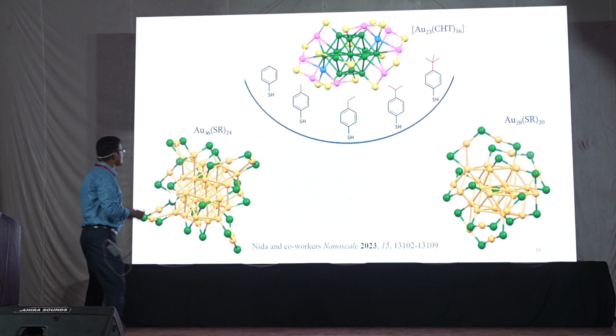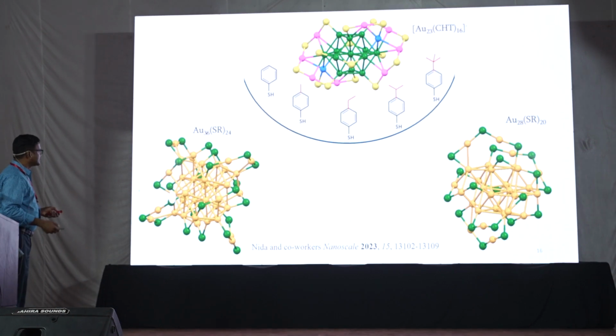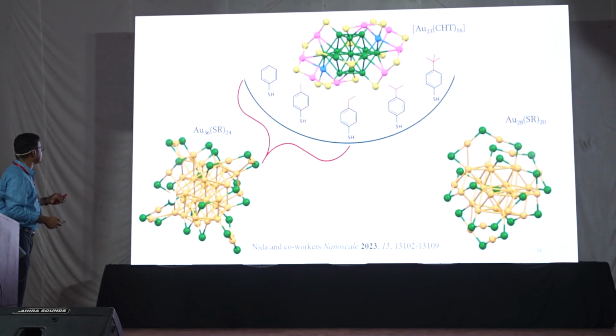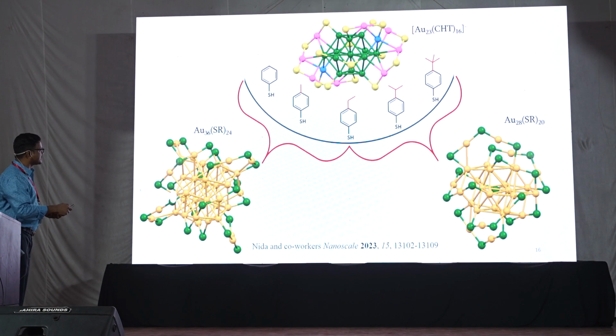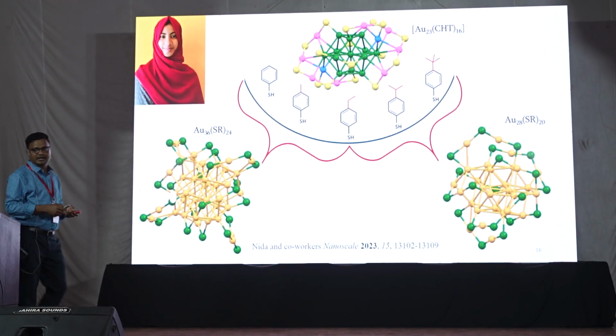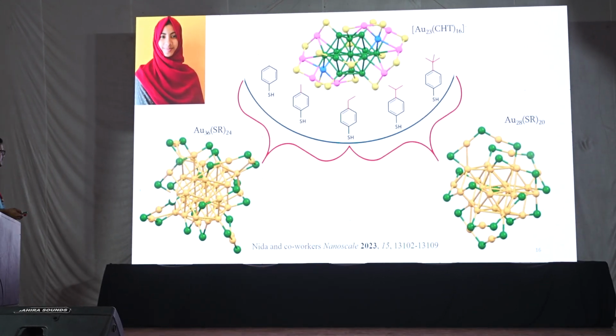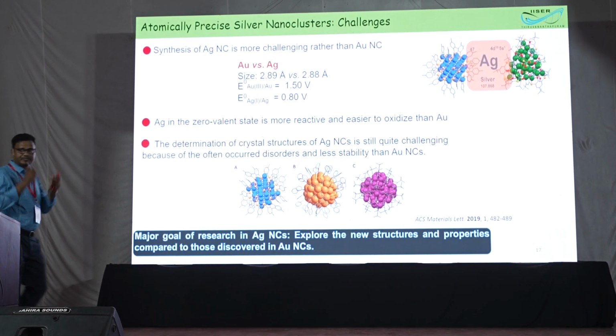So we have crystallized all these cases, and we can see that the two extremes happen when you have the benzene thiol: the 36 yield is decreasing, and the 28 yield is increasing. This work was carried out by your alumni, Nida Kinahan. So now I'll talk about silver.